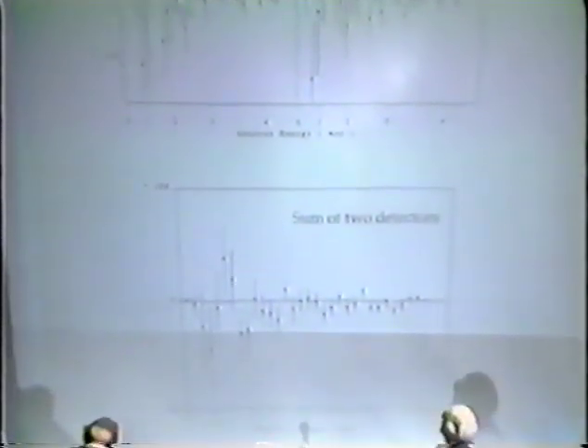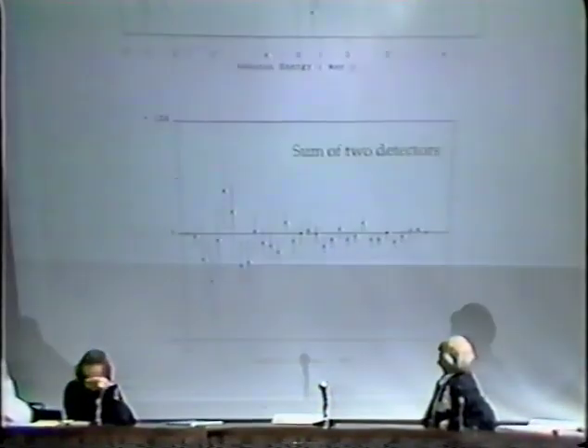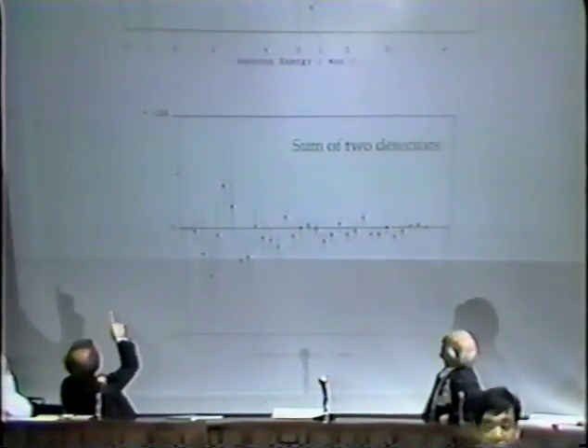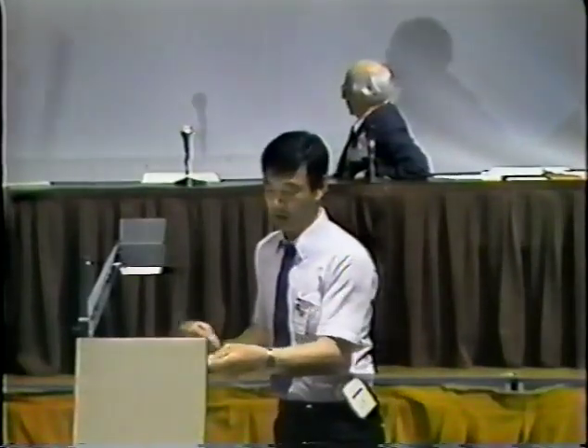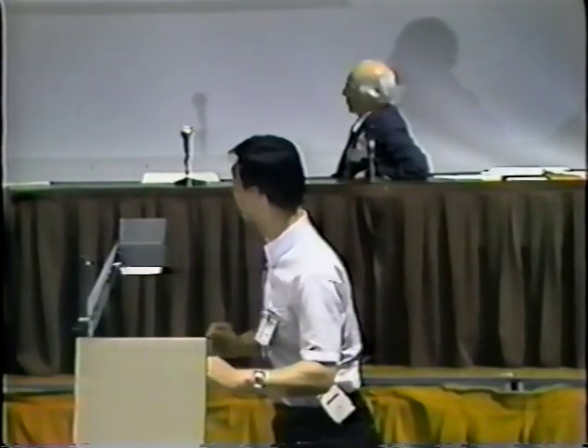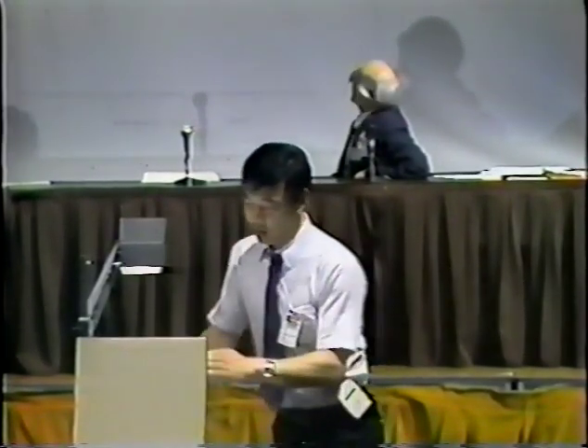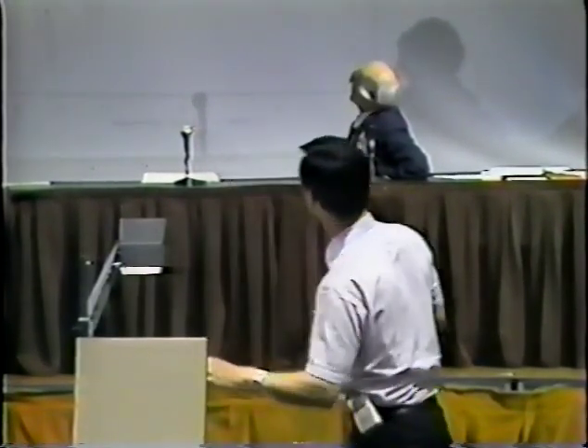And after like 20 hours or so of accumulation, I think we see no sign of the emission of neutrons, even though we use the good sample. I believe that a good sample starts from 0.8 of contents of deuterium. What was the Y scale? Y scale is the count, and count is written in here. It's a subtracted count. So 128 counts per what? It's like 20 hours.